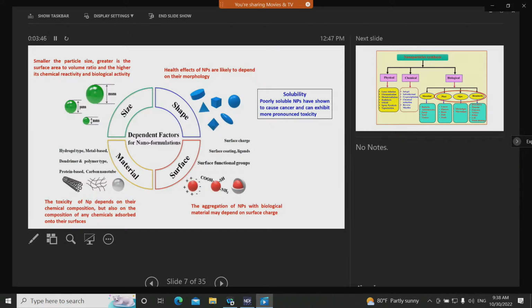And along with the size and shape, surface, because the surface helps in the aggregation of nanoparticles with biological material that may depend on the surface charge, mainly the surface charge or the surface coating, ligands, and the surface functional groups. Finally, the material could be hydrogel type, metal-based, dendrimer, or polymer type, protein-based, and carbon nanotube. So the toxicity of the nanoparticle depends on their chemical composition and also on the composition of any chemical adsorbed onto their surfaces. Along with these dependent factors, solubility also matters a lot because poorly soluble nanoparticles have been shown to cause cancer and can exhibit a pronounced toxicity.